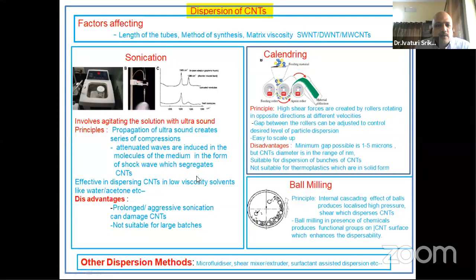So that is one of the methods, but there are disadvantages of sonication. Most of the laboratory methods that were followed employed sonication as a method for dispersion of CNTs. But the problem with this is, this works for some 250 ml or 1 kg of bath. Then you want to make a real big structure.